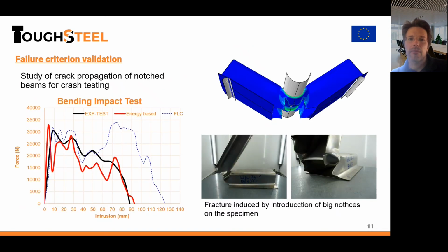The next one, please, David. The model can also be used for crash analysis. In this case, I show the study of crack propagation in a notched beam using a crash test. In the force displacement plot, the black line is the experimental result. The red one is the simulation with our model. And the blue dotted line is the simulation using only the FLC. And you can see that with the FLC, we have an overestimation of the energy in the crash test. And the model works well when the crack starts at the edges, of course.